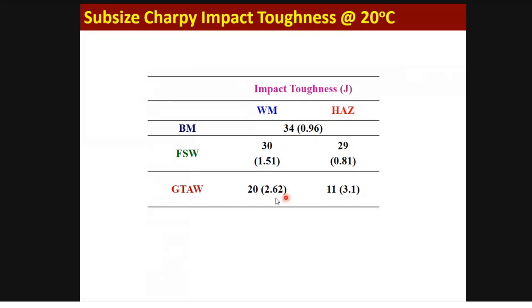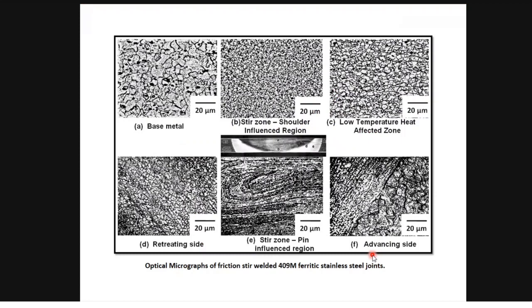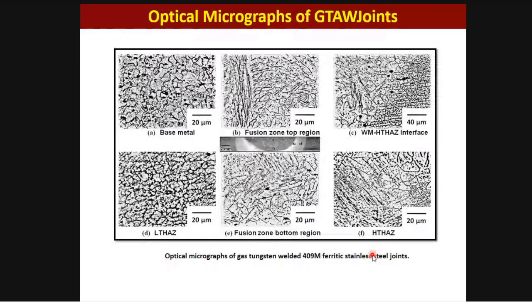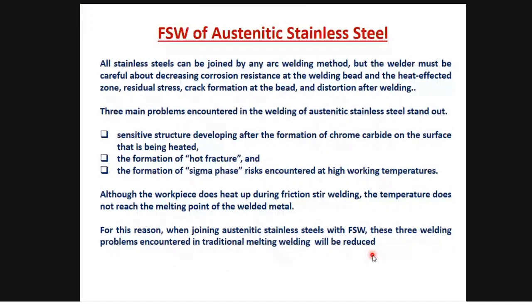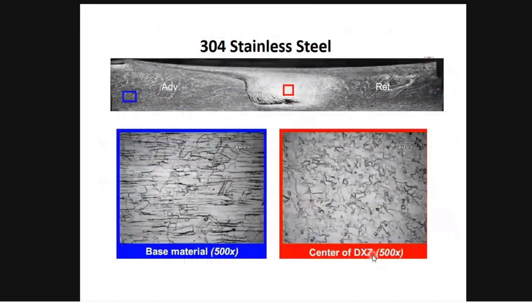But you see that in TIG welding it is much lower, 20 and 11 at the heat affected zone, because of the coarse grains. This is the microstructure of various regions: the pin influence region, shoulder influence region, and then the advancing side and retreating side and low temperature heat affected zone. In these various regions, the ferrite grains are changed, and in comparison the GTAW has all coarse grains.